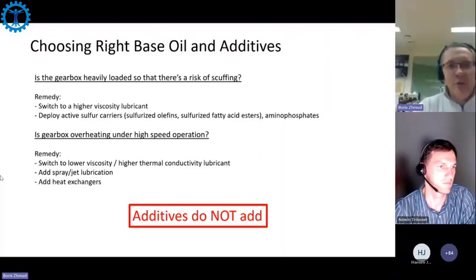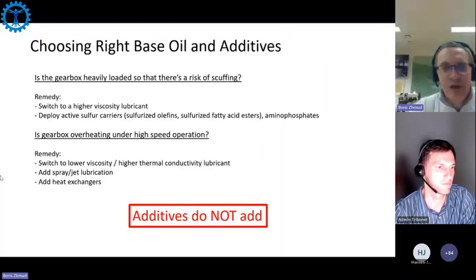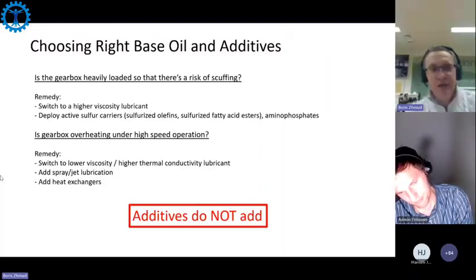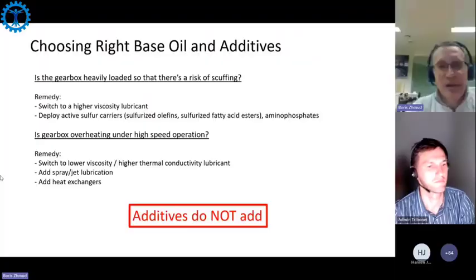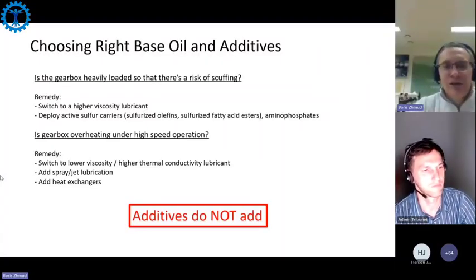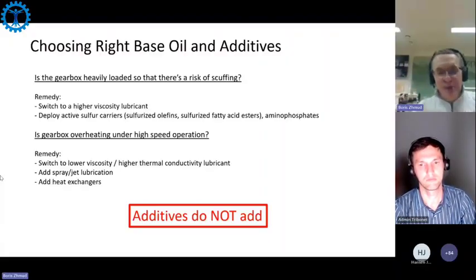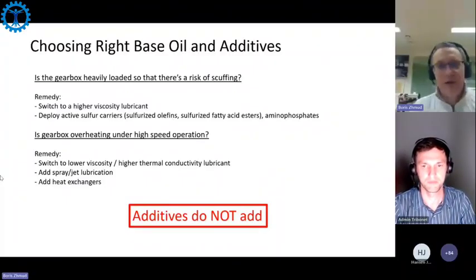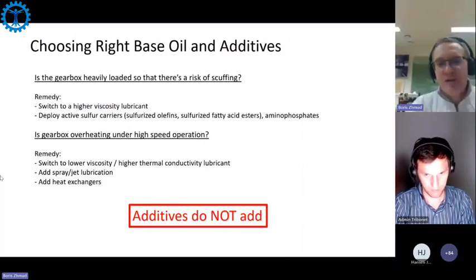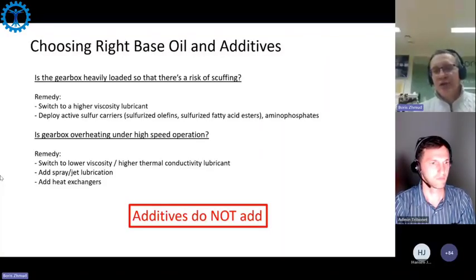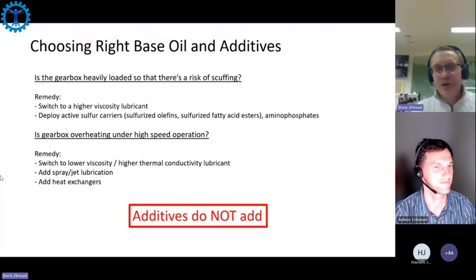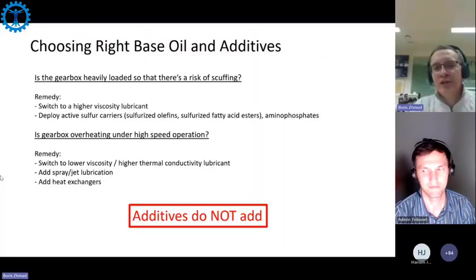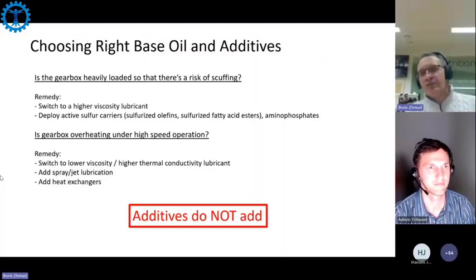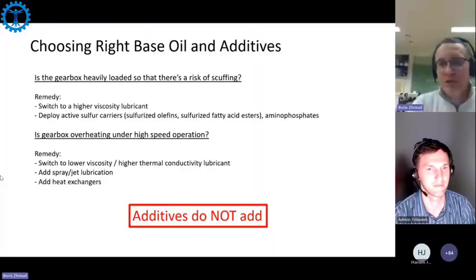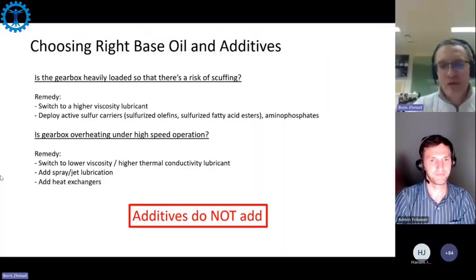On the other hand, if you have another problem, a gearbox overheating at high-speed operation, you need to go to a lower viscosity lubricant or a higher thermal conductivity lubricant. You would probably need to add spray jet or jet lubrication, forced lubrication, to more efficiently drive heat away from the rubbing parts. And you would need to add heat exchangers, because even if you cool it inside, if the fluid accumulates all the heat, it will start boiling and you will get burned transmission fluid. And the most important point is that additives do not simply add. You cannot just add two additives and hope that they will work together. Very often, one additive will kill another. For example, you can go to a glycol-based formulation, and then some of your anti-scuff additives stop working. So you can actually get more problems with scuffing by moving to glycol-based formulations than you had with paraffinic base oils.